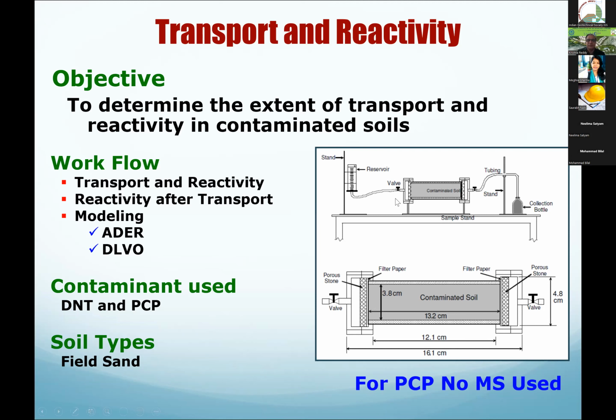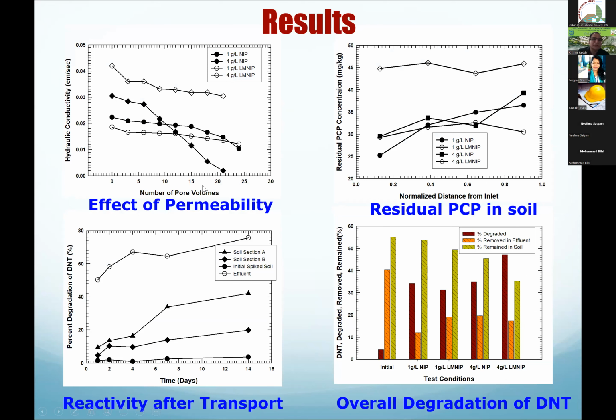Basically, the difference is, before we mixed everything together in a centrifuge tube, right? But here we have a column and we are injecting this one. Before, I showed you the transport experiments where we used the clean sand. Our interest was to look at how the nano iron particles will migrate. The difference here is I am contaminating the soil with a select contamination. Now I'm trying to flush through this one. So now I'm interested in how much it is transporting nano iron particles, and at the same time, how much it is remediating it. How much of the contamination reaction is happening. So we did that one. And also one thing that is important is, as it is transporting, you have a trapping of nanoparticles, and does the permeability change? So this is the interesting results on effect of permeability.